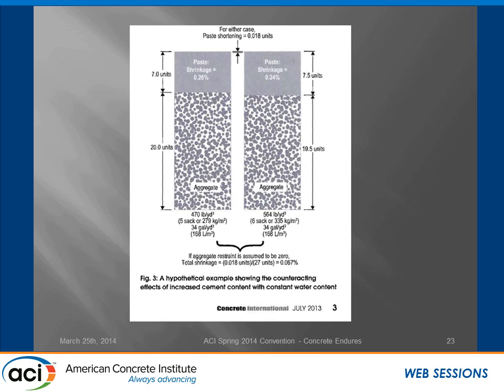And there's the phenomenon they were looking at when they saw the water content. That's what was going on. The excess paste was adding more shrinkage, but it was offset because the water cement ratios were dropping. If you added more water, you added more paste, and you also have higher water cement ratios, so you can see how adding water to the mix will increase the shrinkage. If you keep the water cement ratio the same as you go up, you have more paste. So as you have more paste, you have more shrinkage. And so that's the stuff that they discovered in the 1930s, and how it relates.